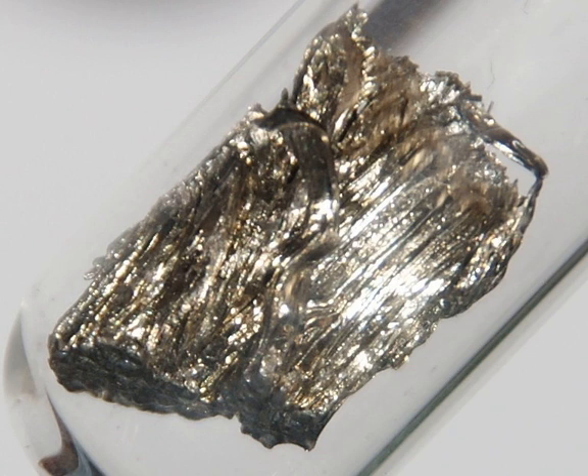Samarium monophosphide, SmP, is a semiconductor with a bandgap of 1.10 electron volts, the same as in silicon, and high electrical conductivity of n-type. It can be prepared by annealing at 1100 degrees Celsius an evacuated quartz ampule containing mixed powders of phosphorus and samarium. Phosphorus is highly volatile at high temperatures and may explode, thus the heating rate has to be kept well below 1 degree Celsius per minute.